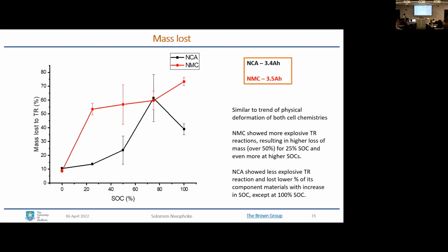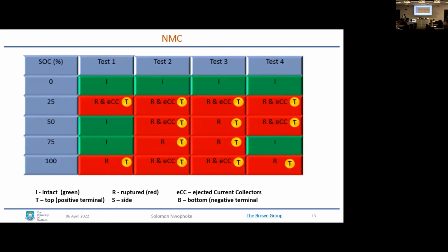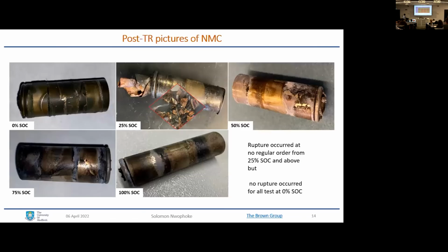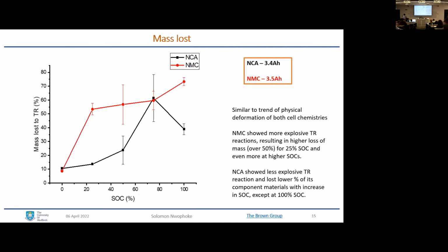Then the mass lost during thermal runaway when the battery ruptures is plotted in percentage, and the red shows that of NMC. You can see larger quantities because, from the last two slides, we saw that most of the batteries here ruptured from 25 state of charge and higher. More of the content was released during the rupture, and that is why you have a high percentage loss in mass, up to 50% for as low as 25 state of charge, and then it increases with the state of charge up to 100. Then for the NCA, it slowly increased at an earlier stage, with state of charge up to 75, and then dropped.